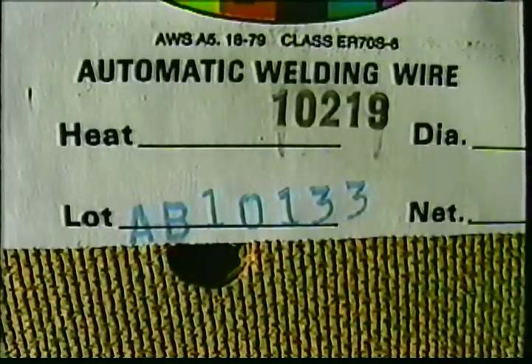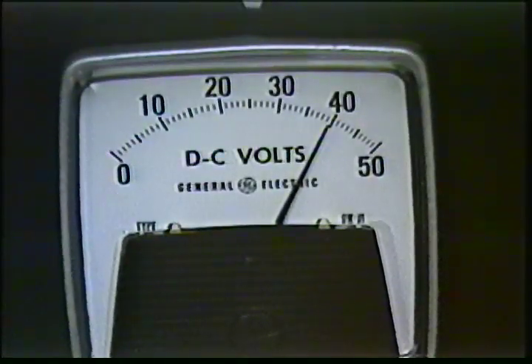Rust and oil on the base metal is a common reason for porosity in the weld metal. Quality wire of the proper AWS classification must be used to produce porosity-free welds. Improper parameters such as high voltage can also cause porosity in the weld.